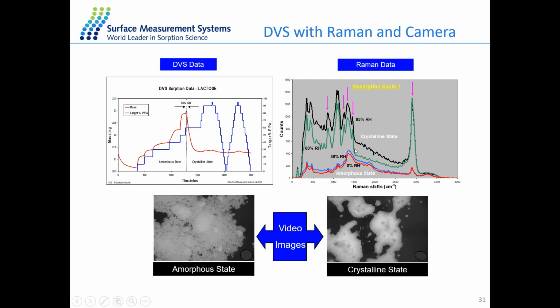So this Raman spectra just confirms the change inside the sorption data, that it goes through the phase change at 60% RH. At the same time, we can also see the amorphous state and the crystalline state in the video image as well. So with those two functions, we can tell at which stage the sample is shrinking, collapsing, or going to deliquescence at different relative humidities, and have a better understanding of the changes in the sample.